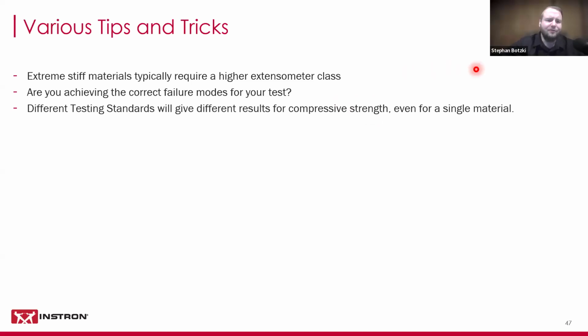It's also important to note that different testing standards will give you different results, for example compressive strength, even if you're testing the same material. So if you're testing with ASTM D6641, and you have a stress value for that, and then you do the same test for ASTM D3410 or ISO 14126, you should not necessarily expect the same compressive strength results. There are different load introductions into the specimens, and therefore also different results typically. So only compare the exact same test types to each other.